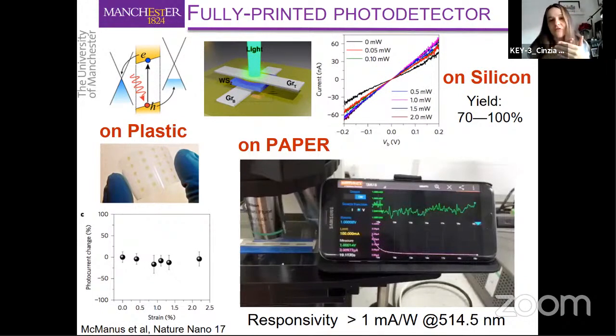And the IV characteristics of all the devices were basically the same within experimental error. So on silicon, we really achieved 100% yield with all reproducible devices, which again shows that our inks have been properly modified and engineered for fabrication of heterostructures. Then we repeated the same type of arrays on plastic, as you can see here, and we studied the changes in photocurrent under bending condition. And as you can see, the device is basically stable up to 2% of strain. Unfortunately, our setup doesn't allow us to probe higher strain.